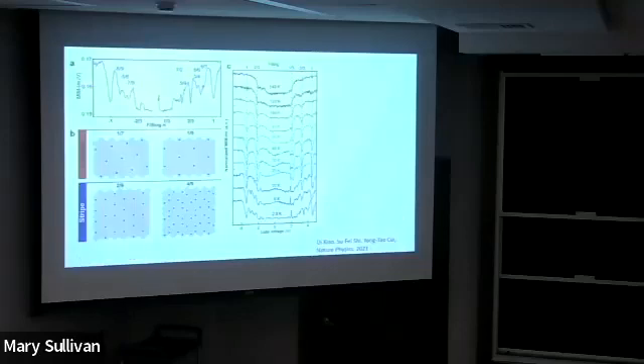But in addition, in a very specific example, we see this really weird feature at 1/7 and 1/9. This is really exciting for a very simple reason. If you look at the configuration, this requires lattice interaction much beyond the nearest neighbor. For this particular case, the electrons are 5 lattice sites apart. Right? It means the interaction is extremely strong. There must be something going on, but unfortunately, this is something we cannot reproduce. We can only see it once. We are still trying to reproduce this one.